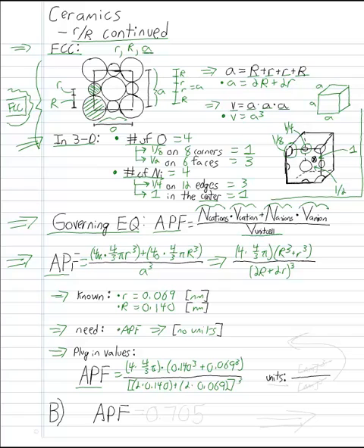That whole expression is cubed. The units for that, we have nanometers, which are cubed since it's a volume, divided by nanometers. Once again, it's cubed. These go ahead and cancel out, leaving us with no units as discussed. Finally then, our atomic packing factor is equal to 0.705.